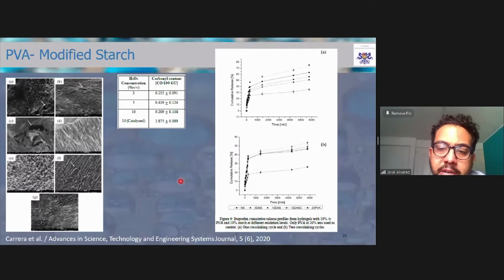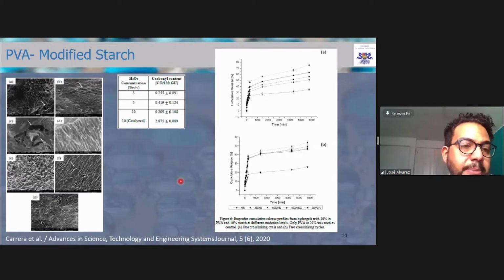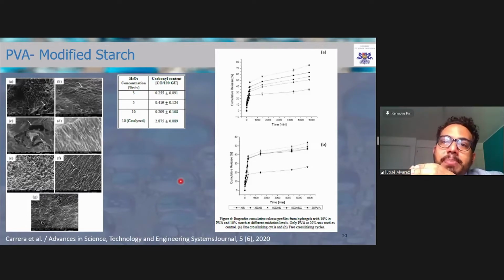Then we also worked, and this is not exactly chronological, but this is a recent paper, actually our most recent paper. We started looking at PVA. Why? Because PVA forms excellent hydrogels, great mechanical properties. They have very interesting properties in terms of drug delivery. But the problem is, to form PVA hydrogels that are stable, you need large amounts of PVA. In the literature, they use up to 35% weight percent of PVA, which would make them actually very expensive for us.